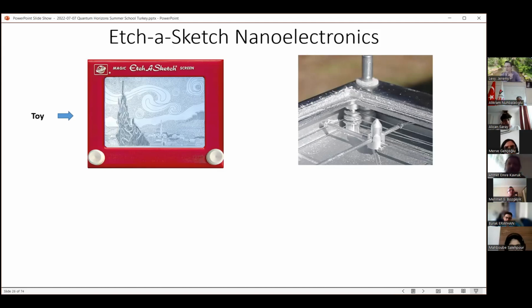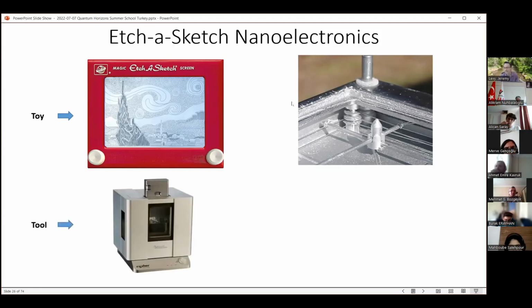So it's a rewritable, actually it's millimeter scale. This is not how they advertise it, but it's millimeter scale control of the metal insulator transition, right? Because the smallest feature is about 1 millimeter, and the aluminum powder is presumably conductive, and then when you scrape away, it's insulating. So you can go back and forth on a millimeter scale. So we were interested in using this as an analogy.